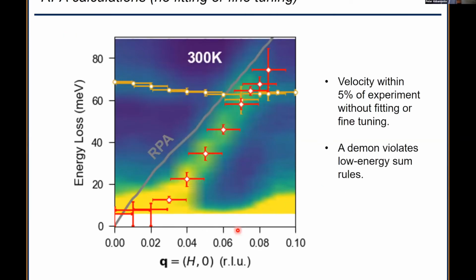Okay, so if you compare that to the experiment, this is the current figure, which obviously we need to improve a little bit before we can publish it. But on the horizontal, again, is momentum in reciprocal lattice units, and the vertical is energy in milli eV. So this now has error bars both in the energy and the momentum direction. By the way, this is just an optical phonon, a well-known mode that you can see with IR. And what you can see is that the velocity of the mode in RPA, without any adjustable parameters, is within 5% of the velocity seen in the experiment. So it really looks like it's the same mode. Now there's a funny issue of q squared down here that maybe we could talk about at the coffee break. But I've never seen such good quantitative agreement between a simple RPA calculation and an actual experiment.